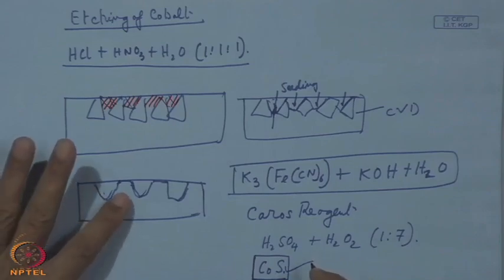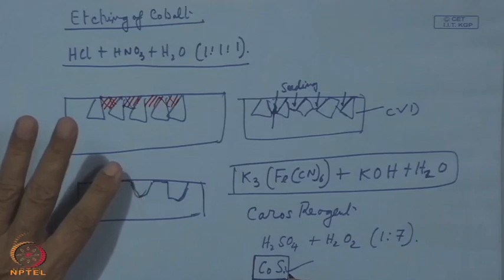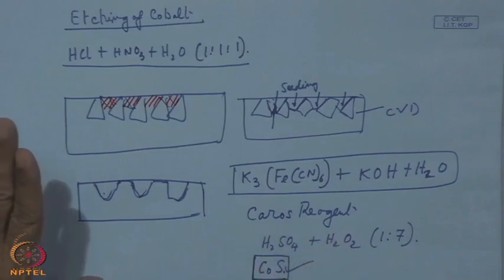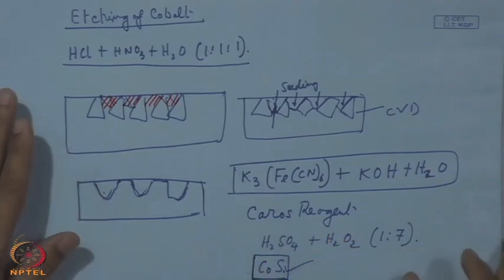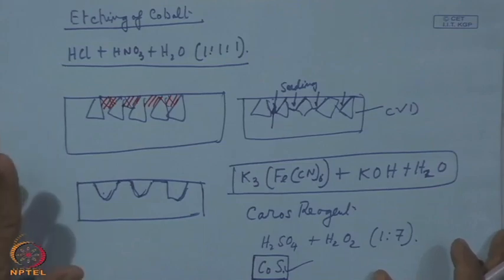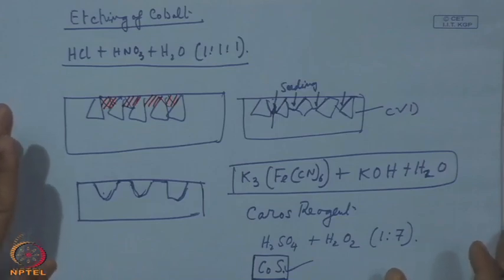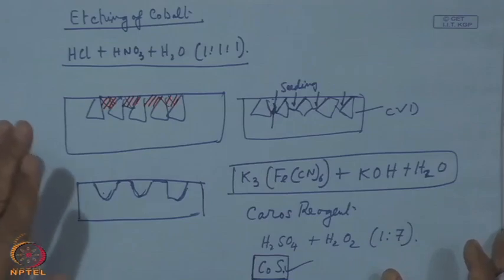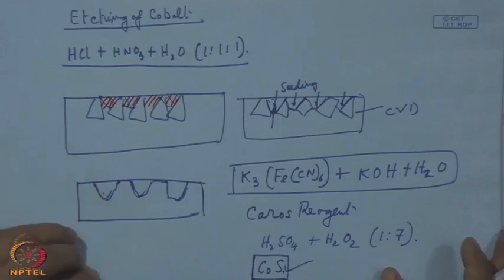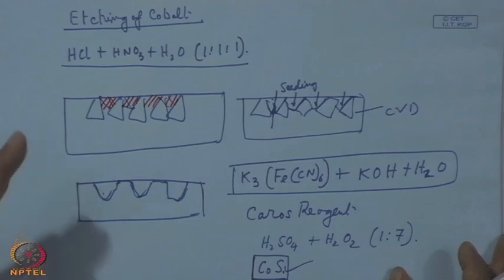That means this cobalt cannot now really do any damage to this diamond surface, and it is well protected. So, this is another way of handling the thing, and as we have already seen, it is a substrate preparation step, which is unlike that of other CVD coating processes, as for example, CVD of TiC or TiN or aluminum oxide. There we do not require that special treatment or special attention so far as the substrate chemistry is concerned.